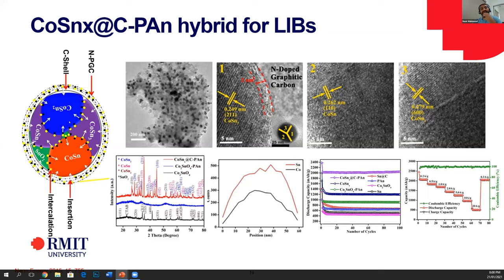If you look at this schematic, you find that we have different phases in a single particle. We have some tunnel boundaries here, grain boundaries, that act as tunnels and allow ions to easily penetrate inside. So what we are doing is using the entire particle to store energy, as well as protecting its surface, and we are not letting any particle changes happen.